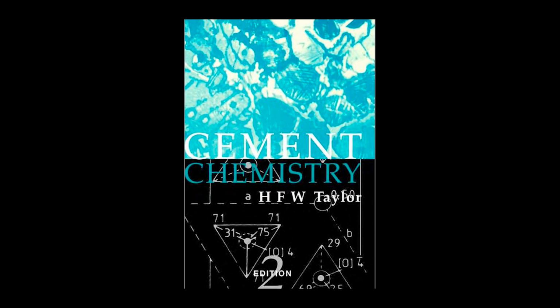Okay, let's talk about superplasticizers, or high-range water reducers. These are perhaps the most revolutionary admixture of the last 50 years. They allow engineers to achieve incredible reductions in the water-to-cement ratio, which immediately translates into strength and durability. How do they perform this magic of liquefying cement paste? Their function is pure colloidal chemistry. They disperse the cement grains.